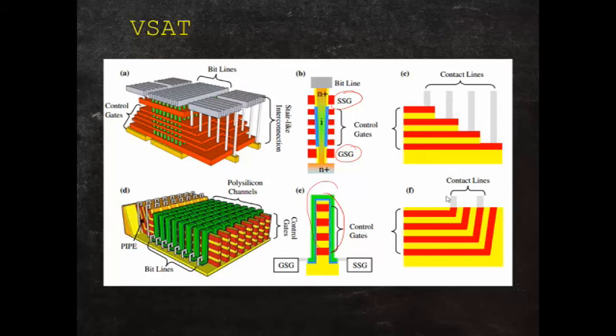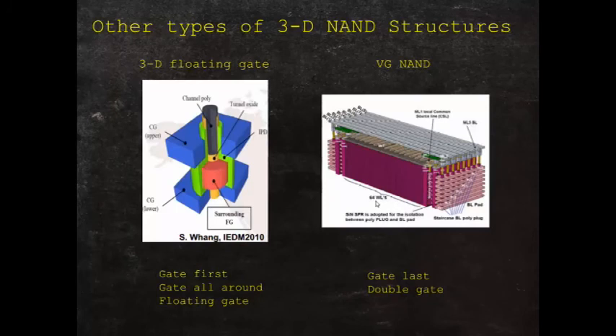What that has the advantage of doing is that now you have a more monolithic construction. You've eliminated the staircase. Instead of having each contact come in in the staircase, you can have the contacts come in on a plane, and this is much easier to land the contacts on a plane than it is on a staircase. Also, you've removed each litho etch step that you have to do to produce the staircase, and so you've come up with a design that may have lower production costs than the BICS design.